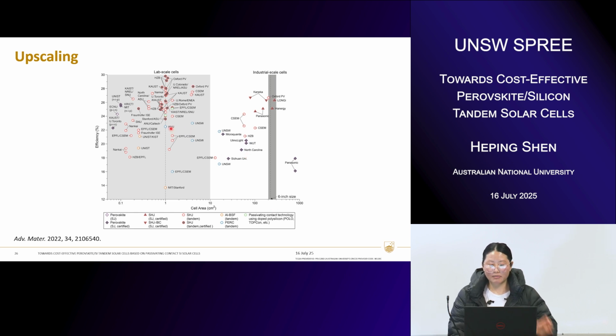First, we can see that the majority of the reported results are still on small area, usually 1 square centimeter. That is significantly lower than what we require for the industrial cell size. Unfortunately, above 100 square centimeters, even above 10 or 20 square centimeters, there are very few reports. So that's a gap. And second, if we look at the average efficiency, there is also a significant efficiency drop during upscaling from 1 square centimeter to 100 square centimeters. For example, on average at 1 square centimeter we can get 28-30%, but at 100 square centimeters that's only 22-25% maximum. So there is significant loss.